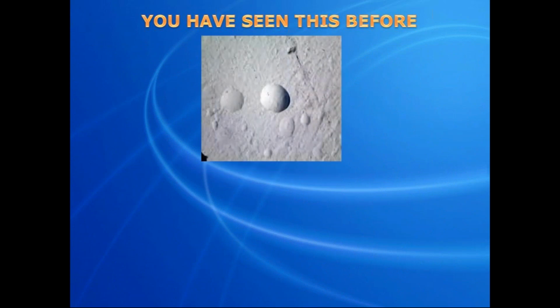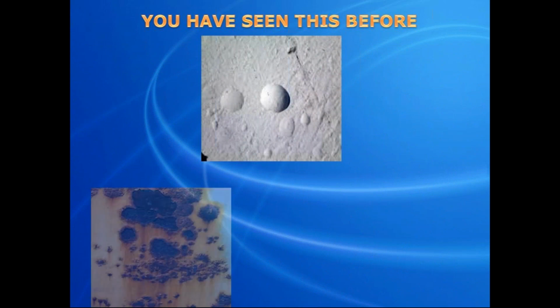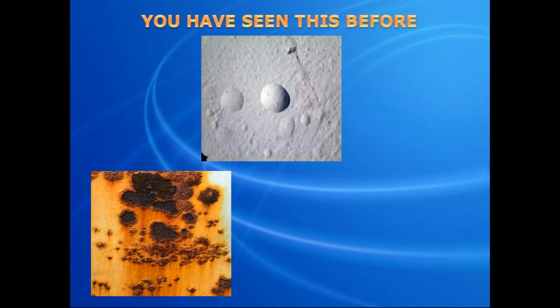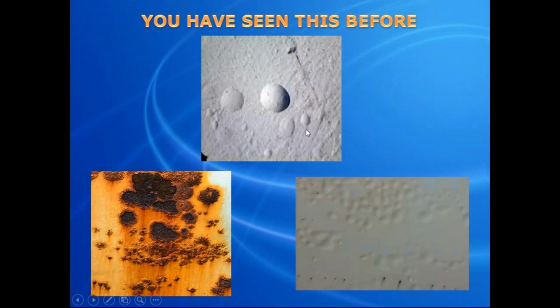Okay, applying coatings over surface salts has drastic effects. Moisture passing through the coating to the substrate where salts remain creates a perfect environment for salt-induced corrosion, followed by osmotic blistering, as you're seeing here, and then coating failure.